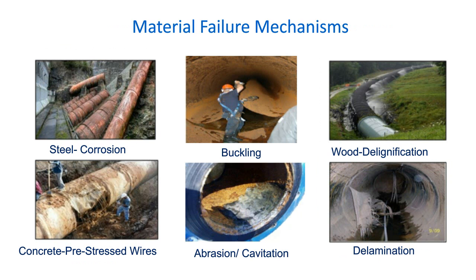And why is that? Well, material failure mechanisms, as you're aware, if it's steel, because of oxidation or redox reactions, I have steel and corrosion. It could be on the surface, on the exterior, or interior. Other things on visual inspections, buckling, if for some reason, maybe if I'm doing my fill and my vacuum or air release valves misoperate, or I pull a vacuum for some reason, I can actually get buckling of the metal itself. An incredible amount of power that can happen in buckling.